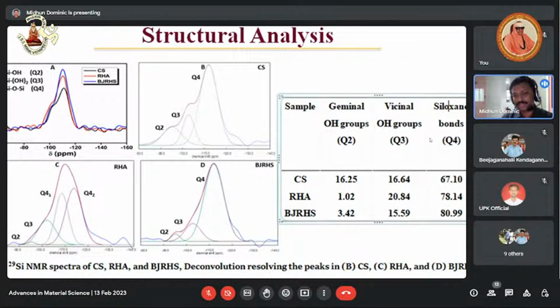But then we formulated another mechanism in our paper: surface area is not the single factor that determines the reinforcement effect of the filler. Along with surface area, we have to consider surface activity too. In order to measure the silanol density, the number of OH groups on the surface of silica, we conducted silicon NMR studies. From the silicon NMR studies, look at the geminal OH group values. The number of OH groups on commercial silica is 16, and for BJRHS it is only 3. So that is a very crucial point in this study.